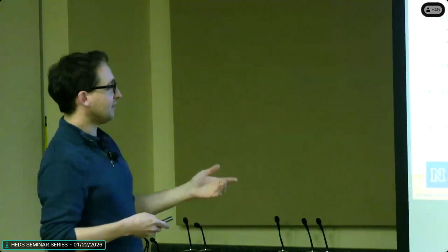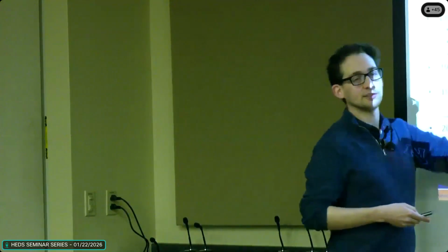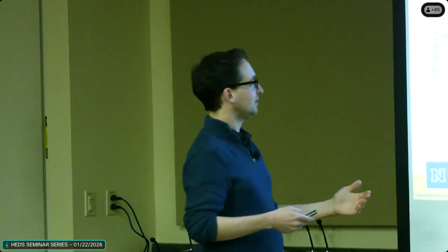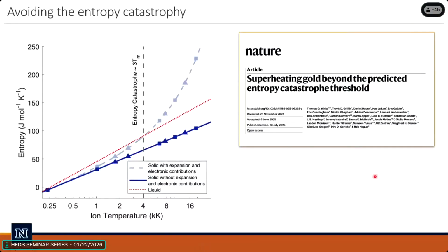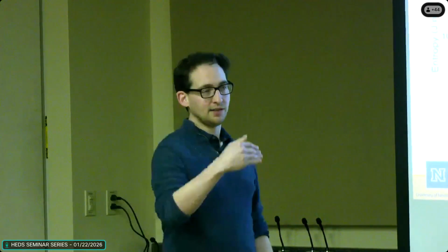In theory, the 3 times the melt temperature should not have been able to be bypassed. You should have hit it and not been able to go past that. But we say in our paper that if you recalculate the entropy lines and you don't allow the target to expand, then the 2 lines never cross. And so instead of suggesting that we broke the entropy catastrophe, which we did not do, what we did was move the entropy catastrophe point up in temperature somewhere else.